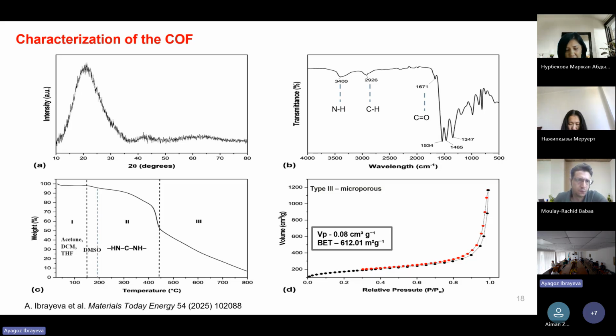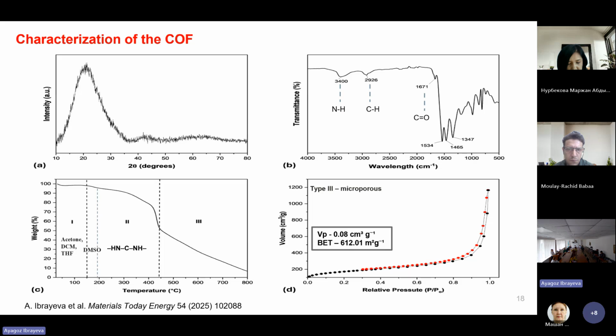And further, we investigated TGA, the thermostability of this material. Here there are 3 stages of decomposition. First of all, gas molecules and physically adsorbed water evaporate. In the second, organic linkers start to decompose. After 445 degrees, this material fully decomposed. To know the surface porosity of this material, we provided nitrogen adsorption-desorption analysis. It shows a classification with type III isotherm without significant hysteresis, and it has a microporous nature.